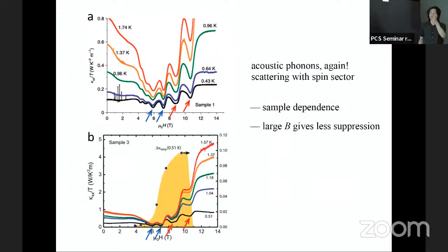By looking at more data, this is data by the same group but another sample, we can find that the dips are still there, but they have very strong sample dependence. This suggests that it's phonons, and moreover, phonons scattering with spin degrees of freedom. Why is the phonon scattering with a spin degree of freedom? Because one common feature of the data, although the details are different,